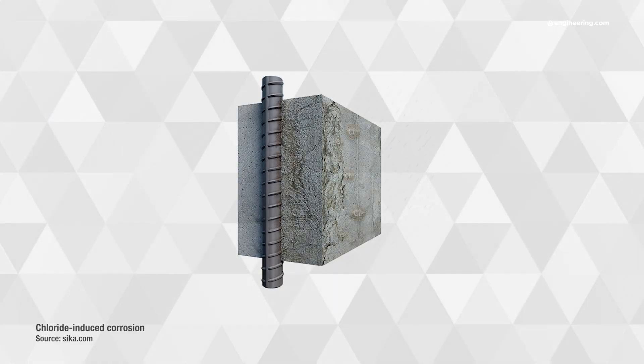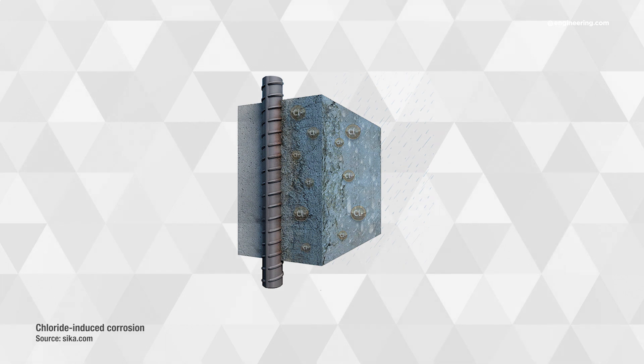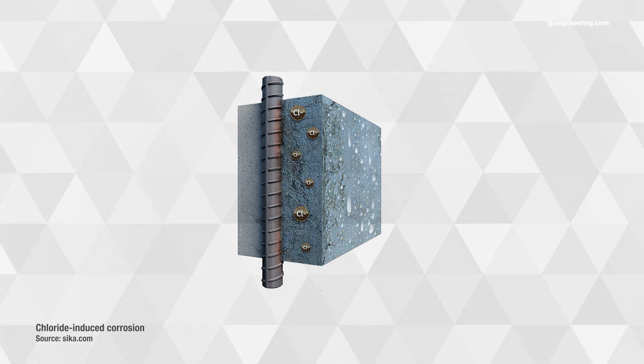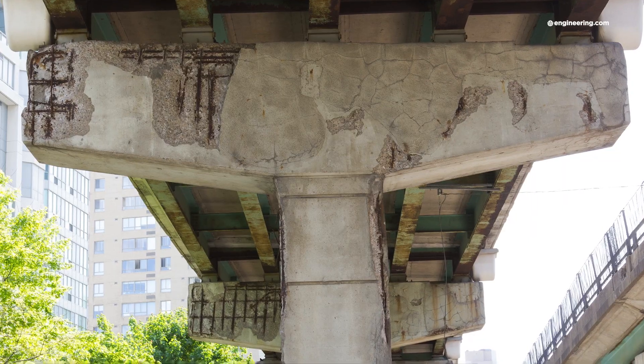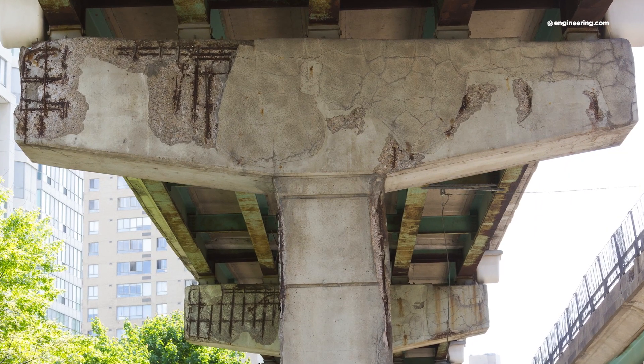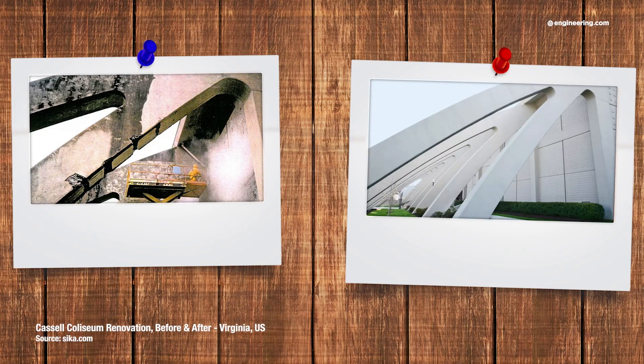Unfortunately, the iron oxide produced by the corrosion of steel is greater in volume than the base metal that it corrodes. And since the bars are constrained by the concrete matrix, the pressure buildup is enormous. This creates a phenomenon called oxide jacking. For bars near the surface, this can cause spalling, something seen commonly in aging reinforced concrete bridge structures in America. Deeper inside the column or beam, the stresses can create extensive cracking, letting even more moisture in and accelerating the process.